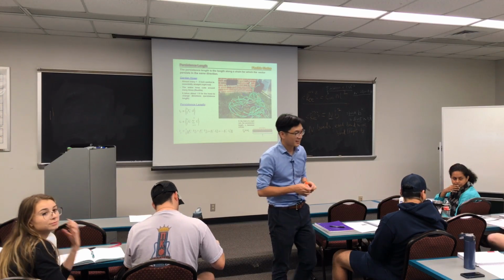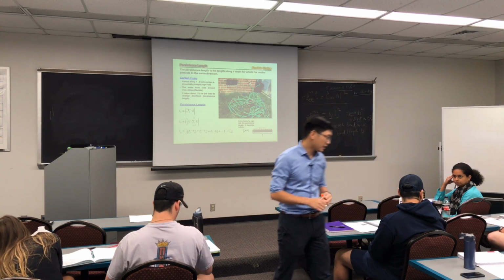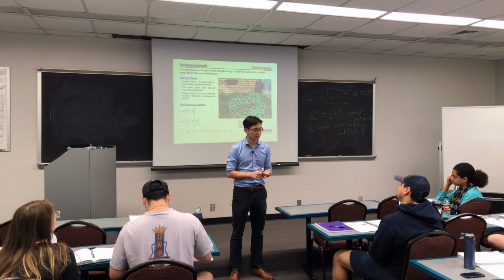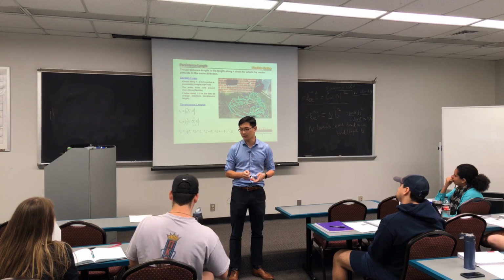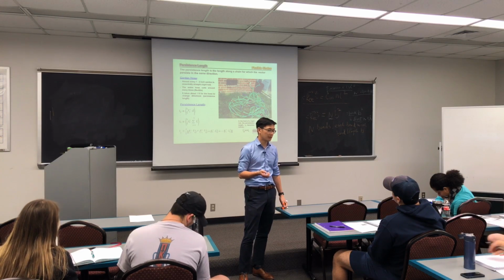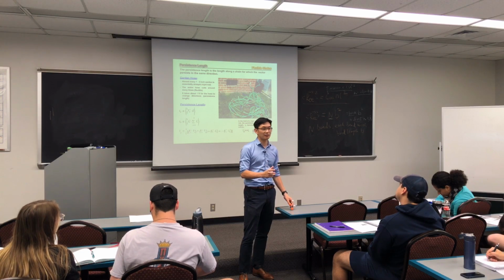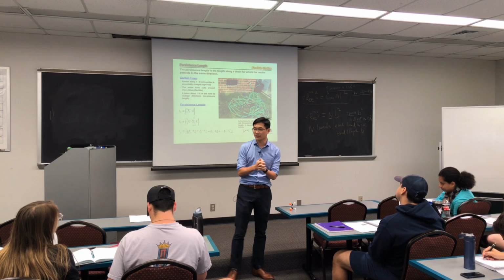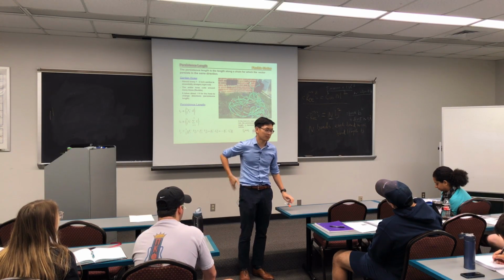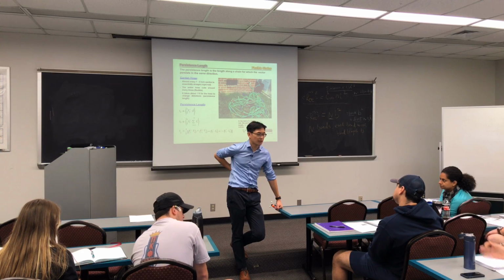Sophia, you have a question? So we can say the persistence length can be used to measure the degree of flexibility? Yes, you certainly can do that. And it's actually intercorrelated with the characteristic ratio. Persistence length and the characteristic ratio are effectively talking about the same thing, and we will discuss in the next class why that's the case. If you have a rigid chain, you would have a large persistence length and a large characteristic ratio, okay? So C infinity will be bigger. That's understandable because C infinity is some sort of expansion factor for the whole chain. If you have a rigid chain, your end-to-end distance will increase. We will spend the next class discussing rigidity and how we can get the persistence length for various polymers.